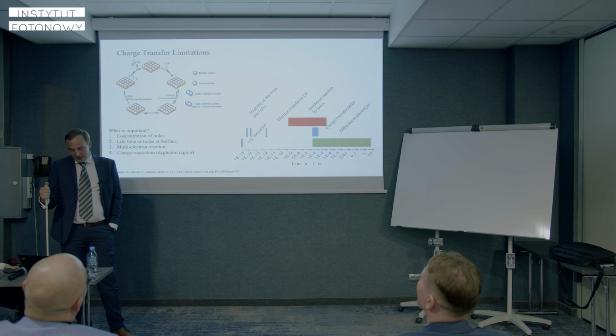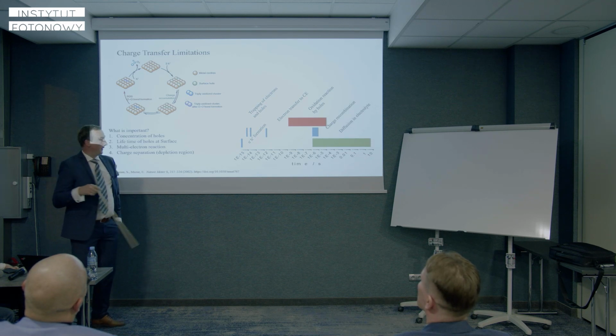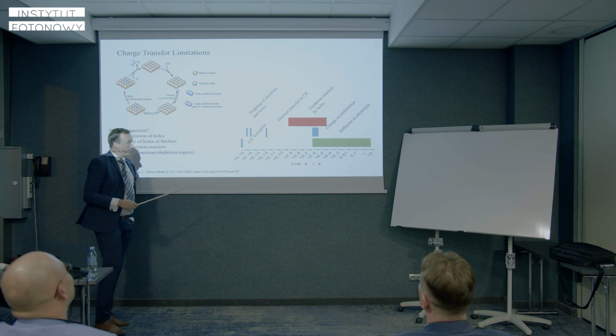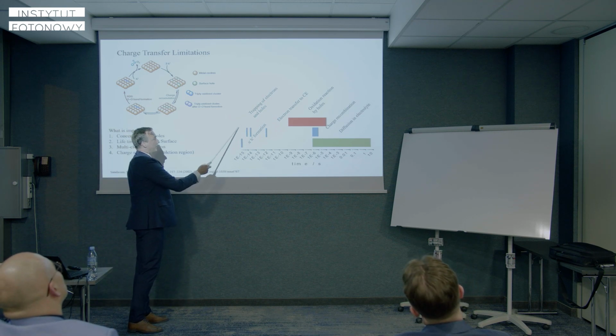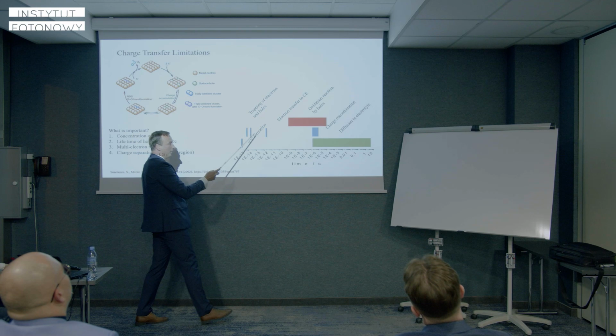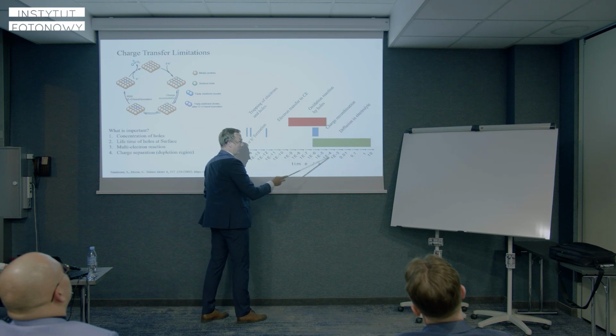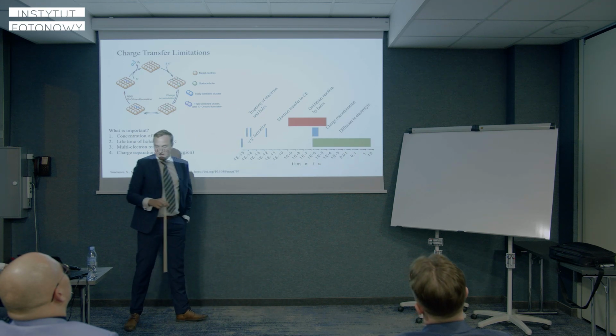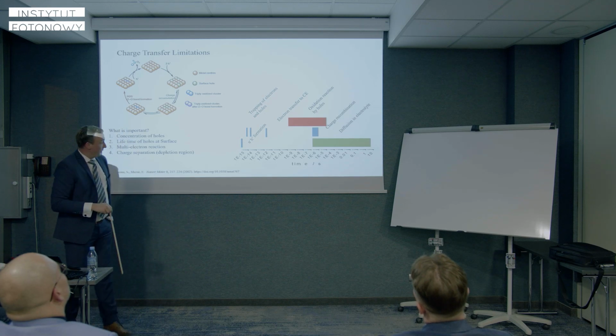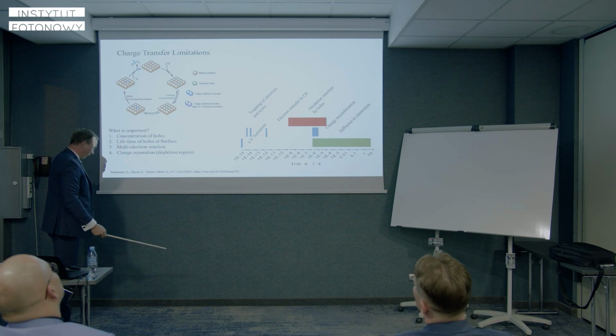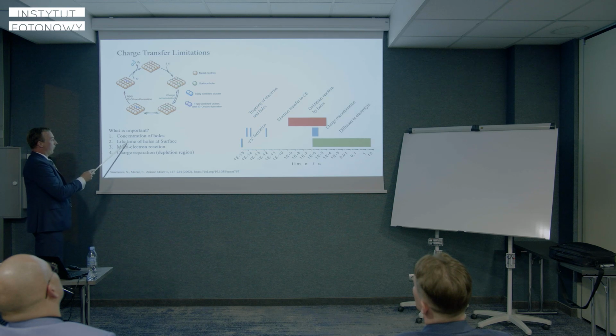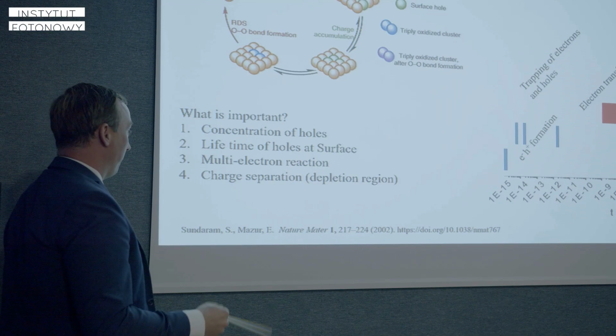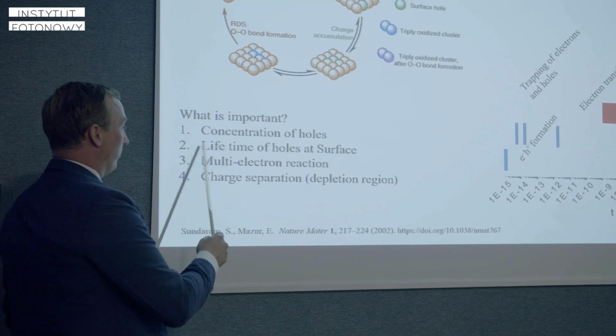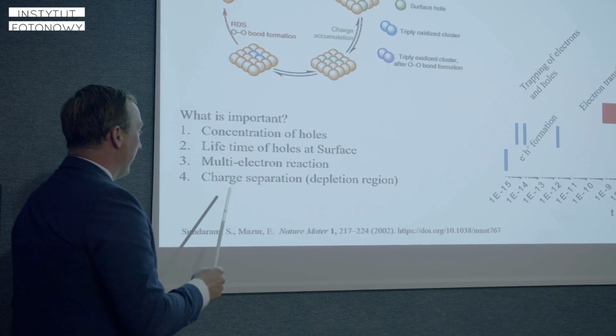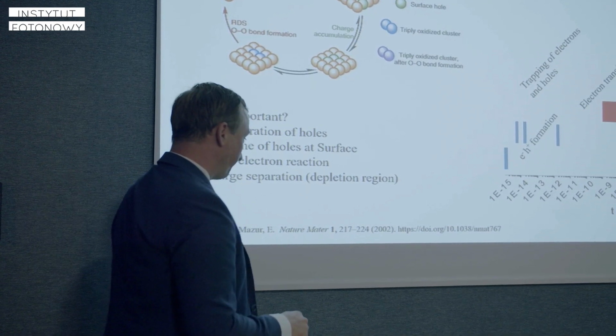Okay, the time course of the process during the photooxidation of water is shown in this figure, and the fastest is the electron-hole formation, and the most time-consuming is the diffusion in the electrolyte. So the most important thing during the photooxidation is the concentration and lifetime of holes at the surface. Also, multi-electron reactions and charge separation are possible.